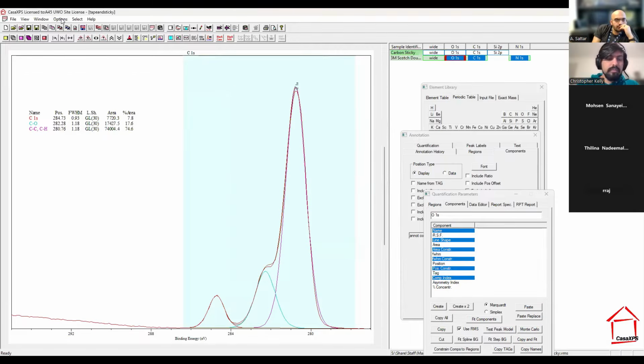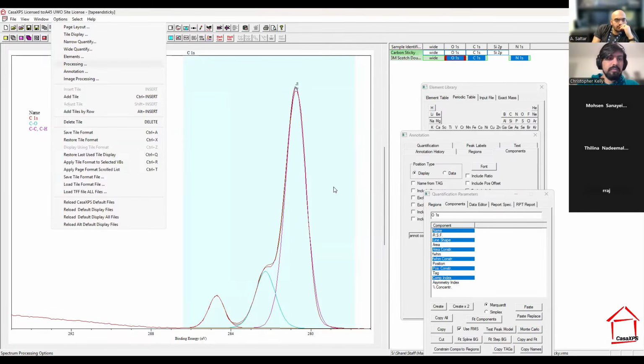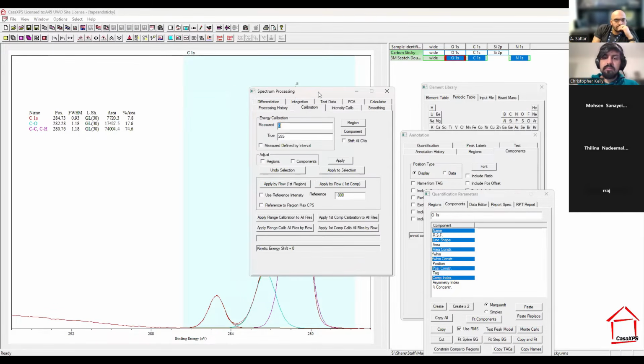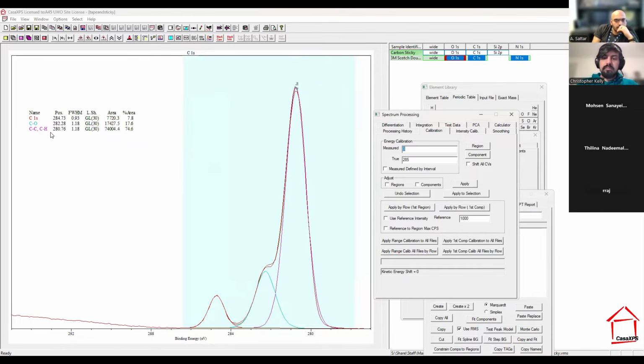Where is my processing? Sorry. And we're going to go calibration. And we're going to take the measured peak, so this aliphatic peak at 280.76, and we're going to charge correct to 284.8 eV. And we're going to shift everything, and we're going to apply this to our selection. And so now we'll shift this peak up. So now this is charge corrected.